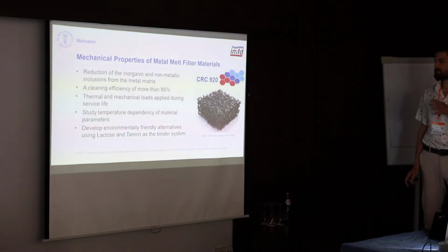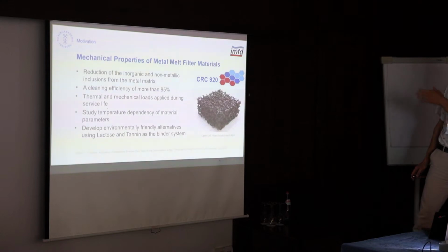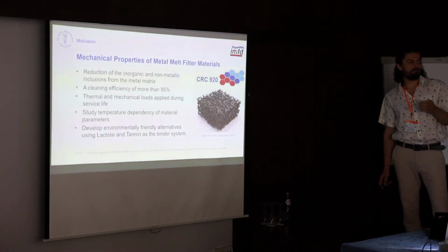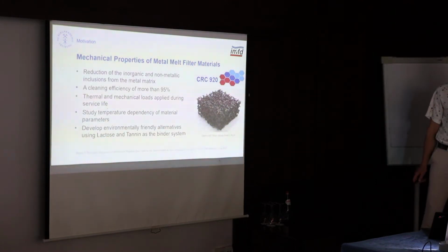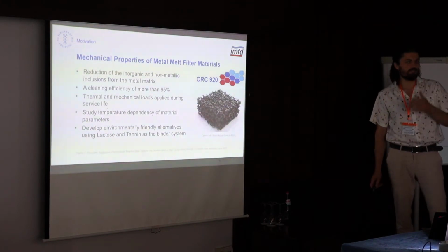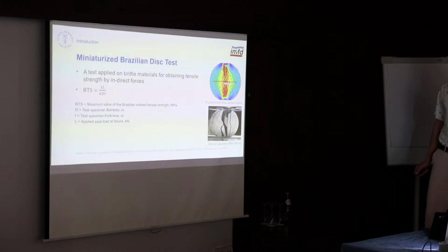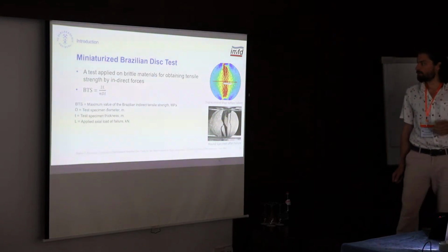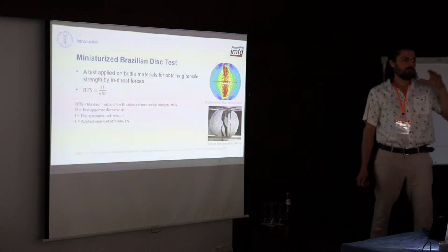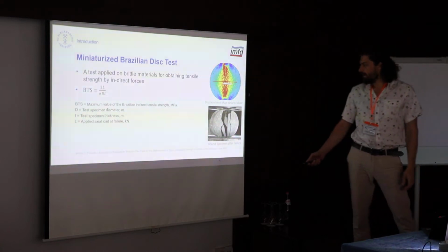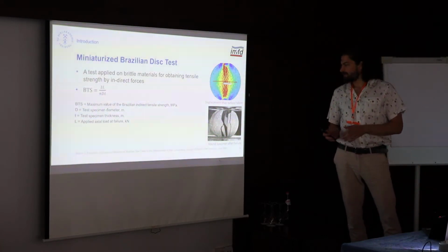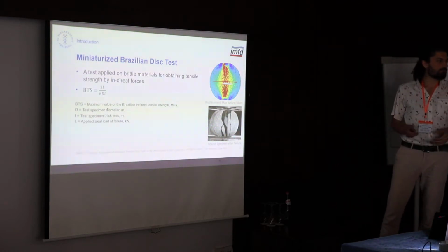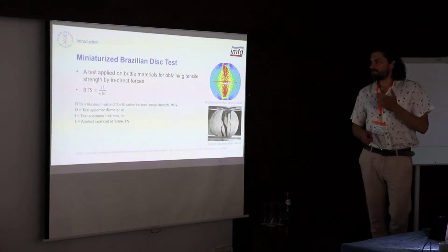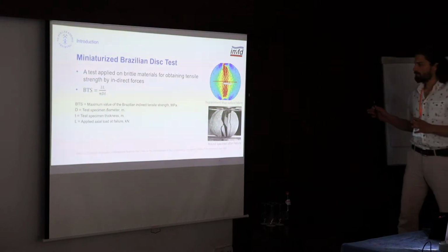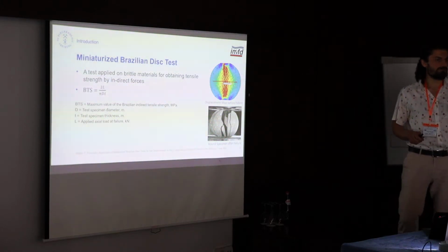And my talk is based on comparison of this carbon bonded alumina and two different lactose and tannin based carbon bonded aluminas with different lactose to tannin ratios. So I used the Brazilian disk test in this work, and it is a well established, kind of old test which compresses the specimen, and these compressive forces cause indirect tensile stresses along the vertical axis of the specimen, which splits the disc into two halves, and the Brazilian tensile strength is a function of the specimen radius, thickness, and the final load at which it breaks.